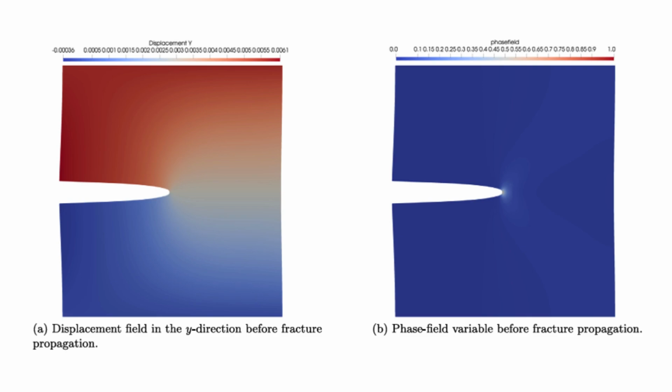Let's see the numbers. How bad was it in that simple bar under tension example? Okay, so for most of the simulation, before the crack really took off, it would converge super fast, like less than 2 iterations of that back and forth cycle, 2 loops. Very efficient. But at the single simulation step where the fracture started propagating rapidly, step 50 in their run, the number of iterations needed to converge suddenly jumped to 82 iterations.